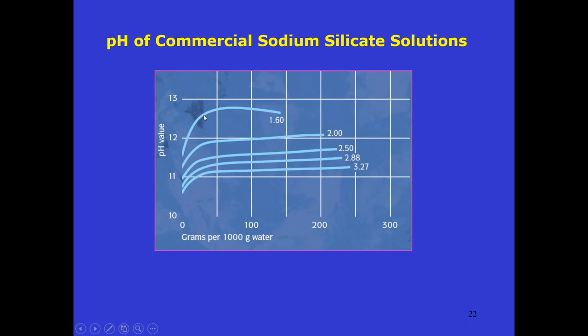In the sense, if you take a 10 molar solution of sodium hydroxide, generally we use, the pH is 15 there. But when you mix with sodium silicate, it comes down to a very small value. So let us remember that we are talking about a mixture of very low pH value compared to the sodium hydroxide. So don't think that sodium hydroxide is meant for creating the molarity. No. But we have to characterize the sodium hydroxide, that's why we call it molarity.